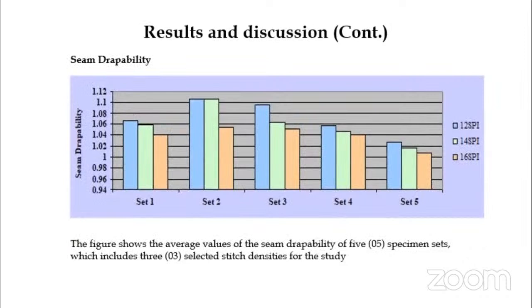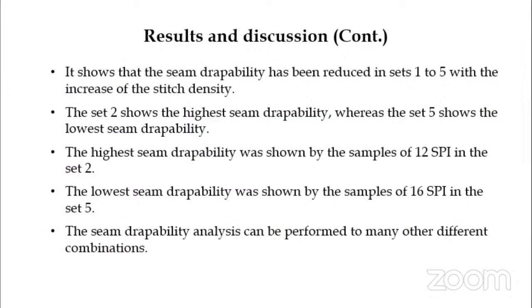This figure shows the average value of seam drapability of 5 specimen sets, which include 3 selected stitch densities for the study. It shows that seam drapability has been reduced in set 1 to 5 with the increase of the stitch density. The set 2 shows the higher seam drapability, whereas the set 5 shows the lower seam drapability. The higher seam drapability was shown by the samples of 12 SPI in the set 2. The lower seam drapability was shown by the samples of 16 SPI in the set 5. The seam drapability analysis can be performed to many other different combinations.